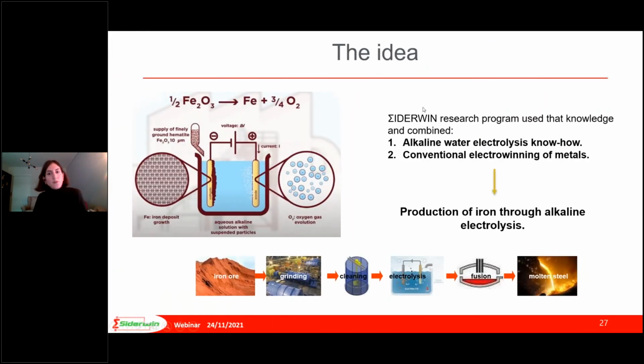So, the Siderwin process combined the previous knowledge with a know-how of alkaline water electrolysis, plus the conventional electrowinning of metals, and formed the production of iron through alkaline electrolysis at low temperatures. As the alkaline electrolyte, 50% sodium hydroxide was chosen, low temperatures of 110 Celsius degrees were applied, and finely ground hematite was used as the raw material.